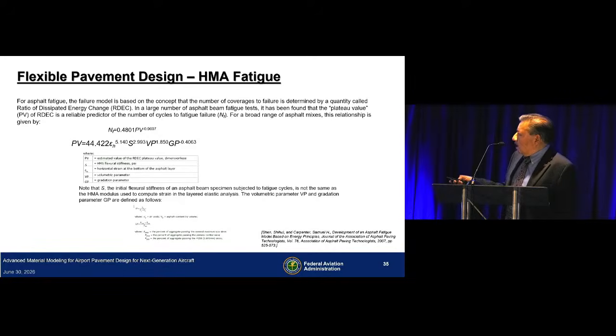The number of cycles to failure in fatigue is a function of the plateau value, and the plateau value is a function of strain in the asphalt, the flexural stiffness, the volumetric parameter, and the gradation parameter. Now, this flexural stiffness, this model was developed based on four-point bending beam fatigue tests.